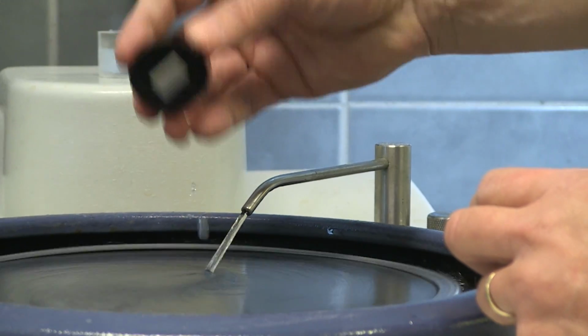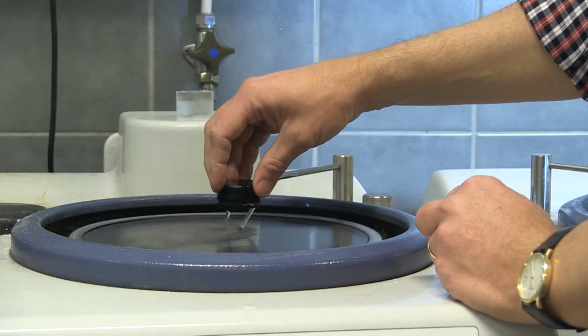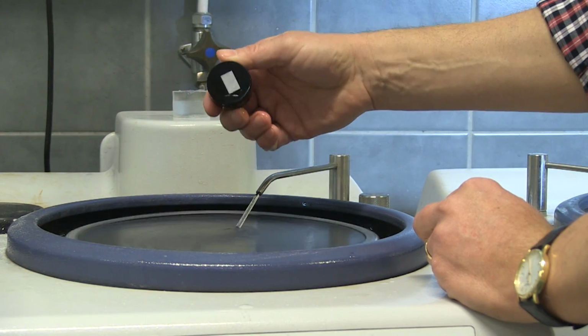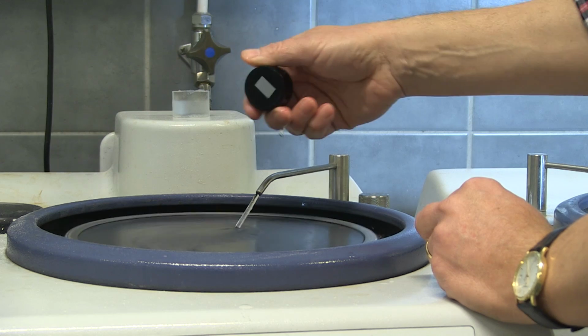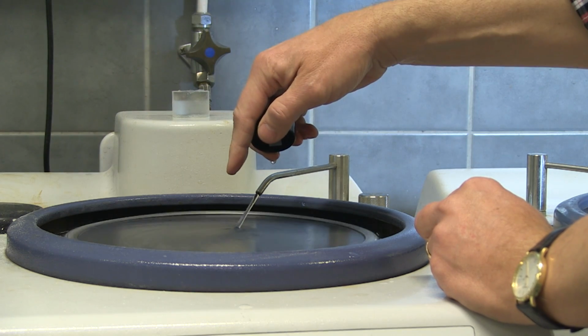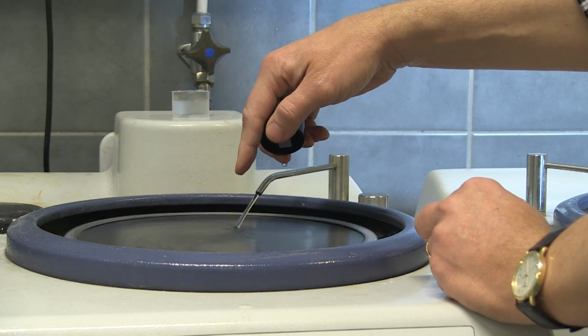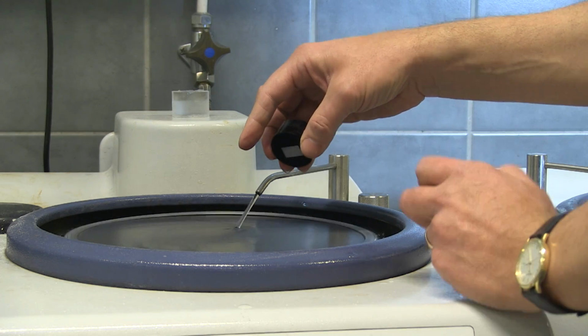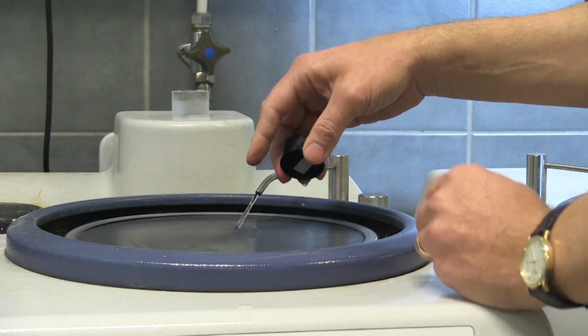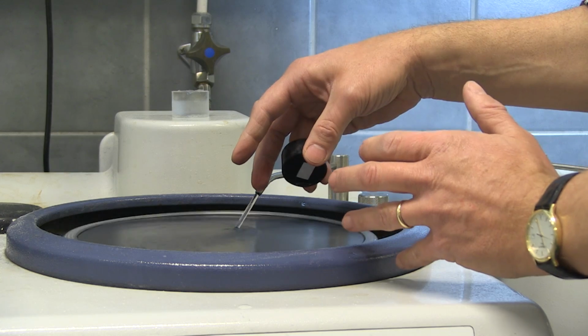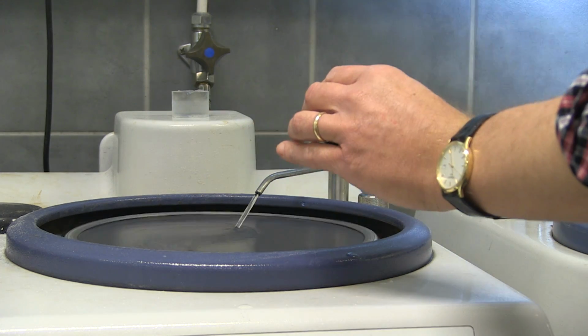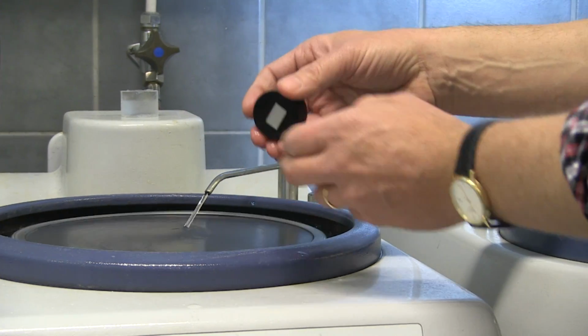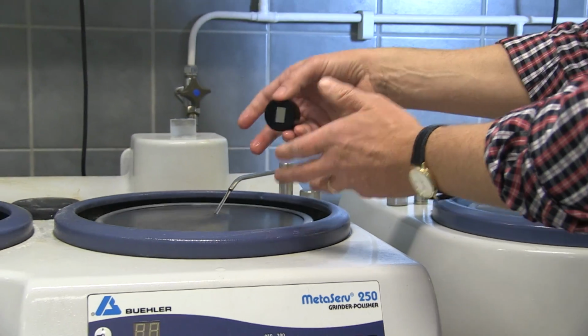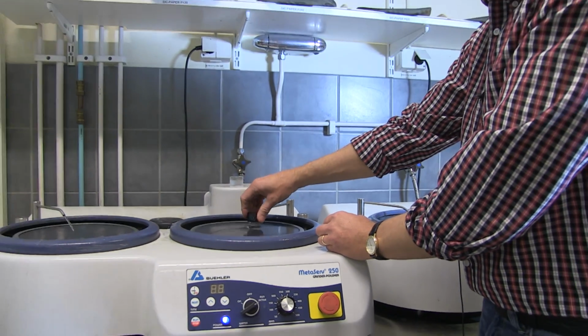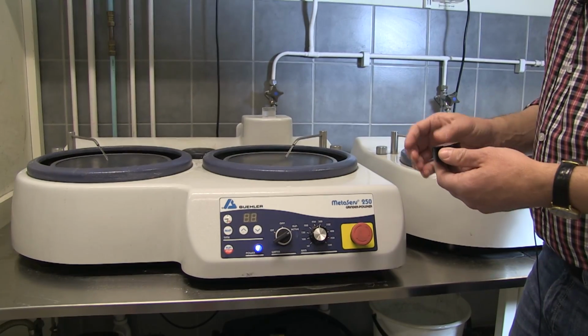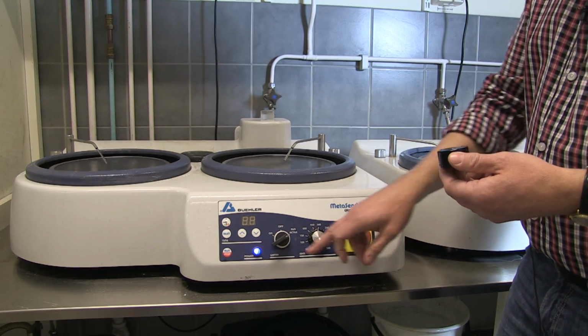I'm rinsing the sample, and I should have told you when I started, it's very important to clean the sample between every step. Otherwise, I will transport these particles, 240 grit particles. If you remember from the paper I gave you, 240 grit particles are about 60 micrometer. I will transport them to my next step, and I will have scratches from those particles on that stage too. So it's important to clean between every step. Moving to the next step, I have to change machine, so I turn this one off.